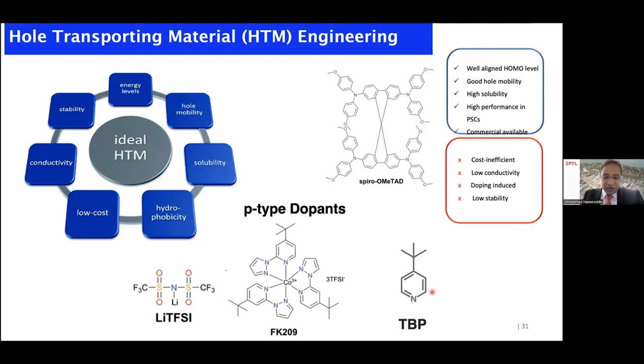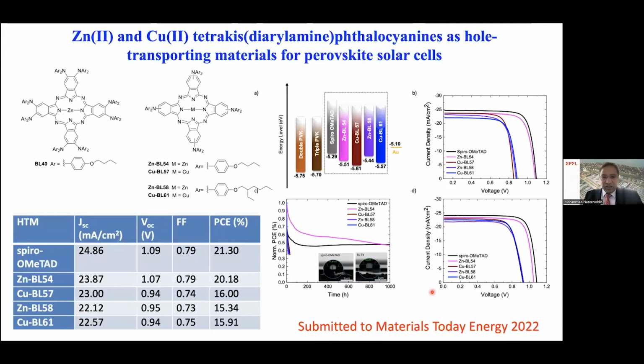So can we change this hole transporting material to a new class of hole transporting materials? This work we just submitted. So here are the phthalocyanines. They are very nice compounds. Phthalocyanines stack together, so therefore they may not require dopants. Here we have taken two types of phthalocyanines, where we change the metal center from zinc to copper, and the peripheral substituents from butoxy to branched alkoxy. So these are the two various substituents on the periphery, and the central metal is zinc or copper. Instead of going through all this data, the take-home message is that zinc-based metal phthalocyanines show the best performance compared to copper-based ones.